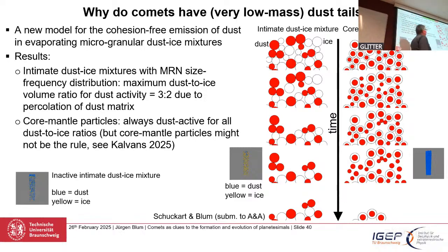As we have a model that works for pure ice, we thought, well, let's apply that model to a comet. So now the colors mean something. The red is a dust particle, the white is an ice particle. So the makeup of a comet is a dust-ice mixture, but we have no idea whether it's what we call an intimate mixture of dust particles and ice particles, or whether the ice is on the surface of the dust, which is the right-hand side. Again, we evolved from top to bottom, evaporating the small ice particles first, evaporating those with the thinnest ice layers first, and follow the emission. So let's do that in some movies.